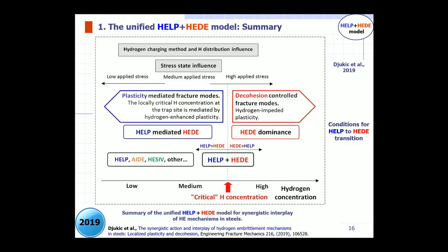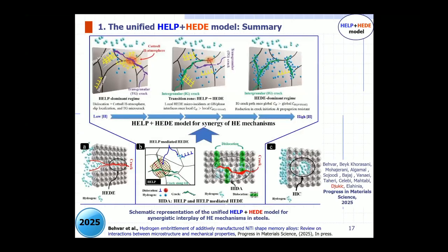So we have a transition to so-called dominance, meaning that decohesion is the major mode in our material. So we have a decohesion-controlled fracture mode, and in that case, on microscopic level, we have hydrogen-impeded plasticity, not enhanced plasticity, which is what we had before, and that's the major trick with hydrogen. Hydrogen embrittlement used to enhance plasticity, and now we have impeded plasticity. We have a change in the effects of hydrogen on metallic material.